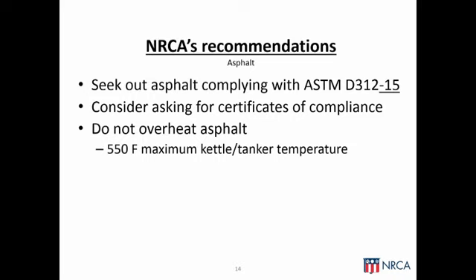The next point I think is fairly straightforward. We want to get away from overheating asphalt any hotter than it needs to be, and at a maximum, the new kettle temperature for asphalt is 550 degrees Fahrenheit. Again, we are of the opinion that we're actually lowering kettle temperatures in the field, and the revisions to the new ASTM standard allow us to do that, which is significant for us from the health and safety standpoint. Next point is something we've been preaching at NRCA for more than 40 years. For built-up roofing application, apply asphalt at its EVT temperature.